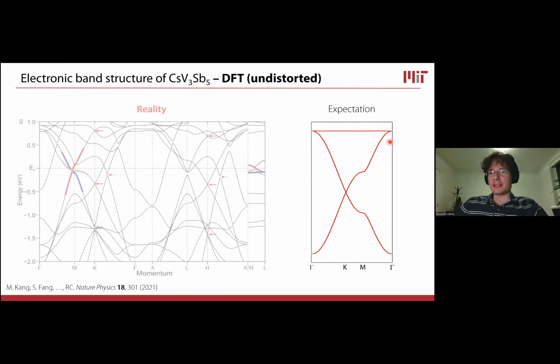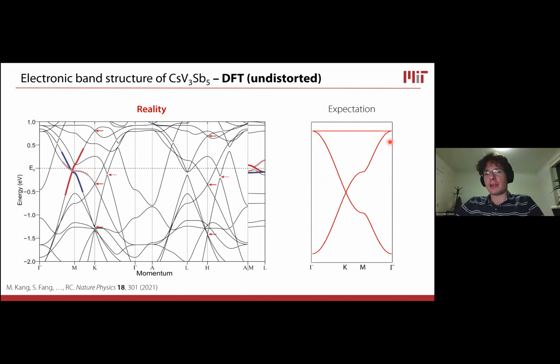So this is the expectation from the tight binding for the band structure of these systems. And this is the reality, which is very different, of course, and much more complicated. So you see a jungle of electronic bands here, but I really want to call your attention to this group of 3 bands, which are highlighted in red, blue, and pink. The really remarkable thing that characterizes these materials is that they have multiple Kagome bands that arise from the fact that we have multiple 3D orbitals from vanadium, and each of those orbitals has its own set of Kagome bands. And they all have a Van Hove singularity near the Fermi energy, which really tells us that there's something special happening here, where these ideal conditions for symmetry breaking are potentially realized in this system.